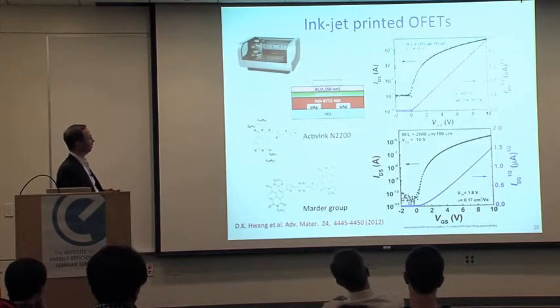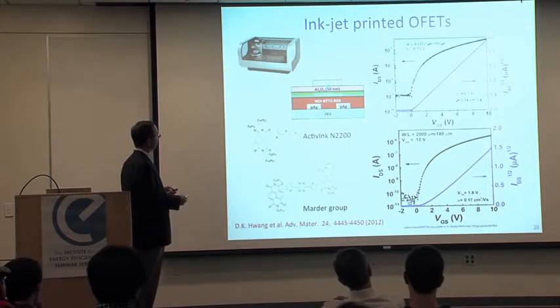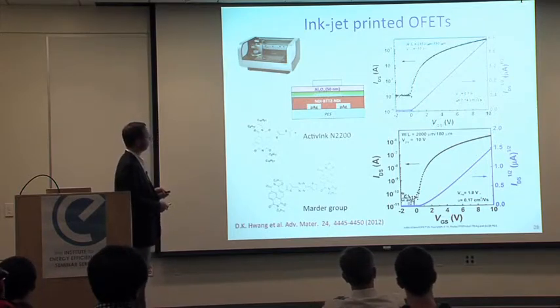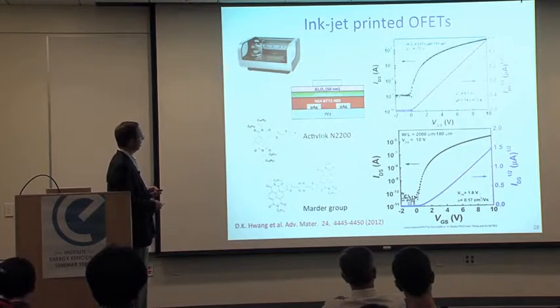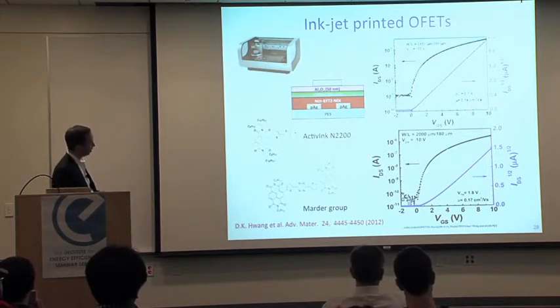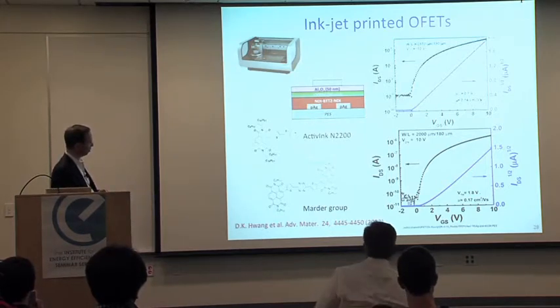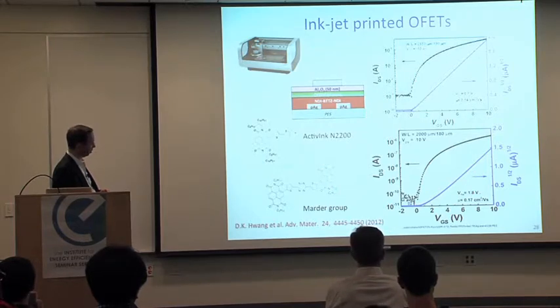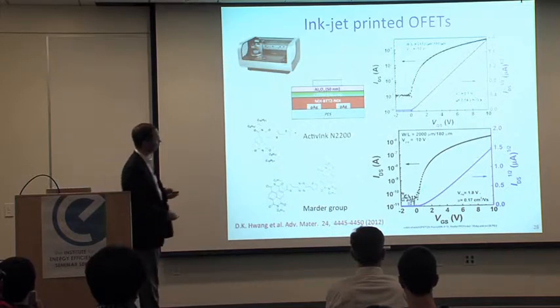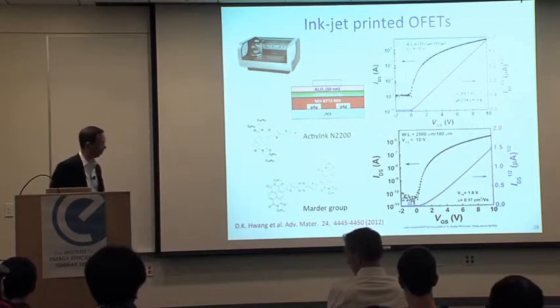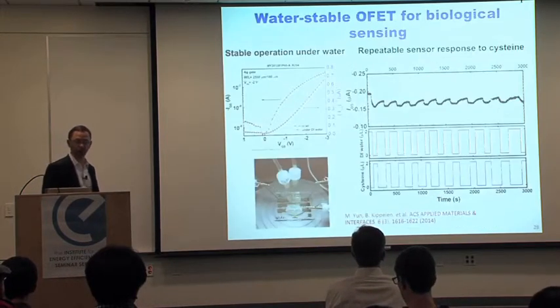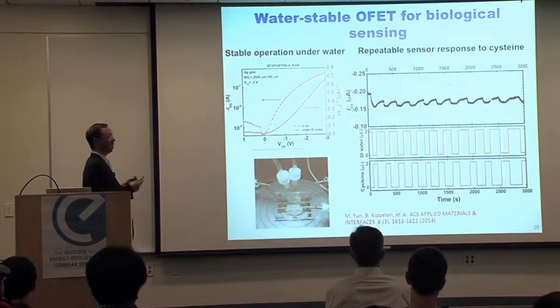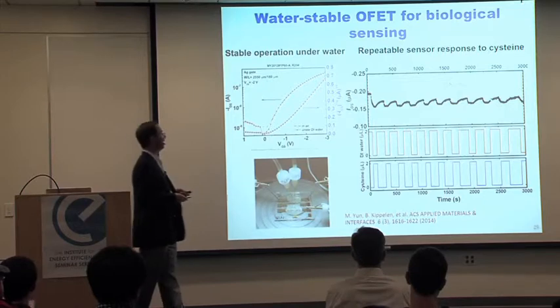This is just to illustrate that we can make transistors with that bilayer gate dielectric that have very clean, very nice transfer characteristics. On top here, this is an N-channel transistor with that commercial ActivInk from Polyera. And at the bottom here, you see another example. It's not as clean as this one. There's still a little bit of contact resistance, but this was done with a soluble molecular compound that was synthesized in the Marder group, and both lead to mobility values of the order of 0.1 to 0.2 square centimeter per volt second.